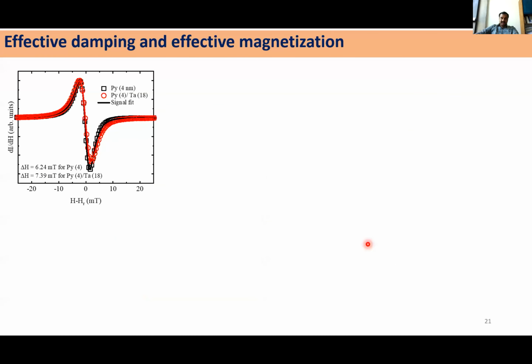width field. Okay, so to find out the effective damping, we took permalloy of 4 nanometer and then permalloy of 4 nanometer with tantalum of 18 nanometer. We see that there is an additional damping that can be seen as a line width broadening.